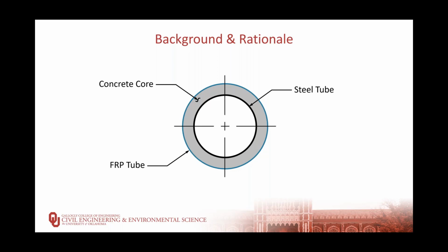The inner and outer tubes also provide confinement for the concrete core, increasing its apparent compressive strength. The steel tube on the inside provides the reinforcement and the ductility for the system, while the FRP tube on the outside enhances the durability because the FRP is resistant to chlorides and other deleterious materials and protects the concrete and the steel on the inside. The concrete core prevents local buckling of the steel tube and the FRP tube, improving their characteristics and behavior.